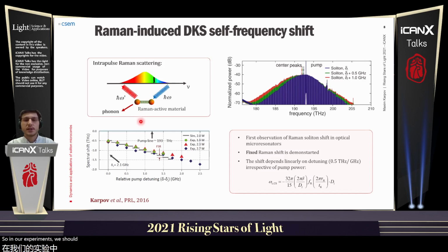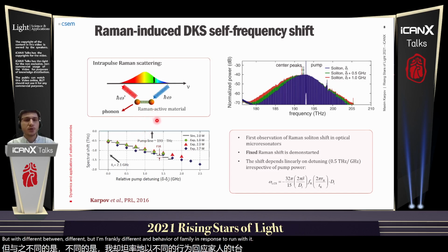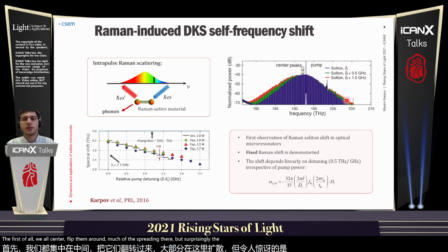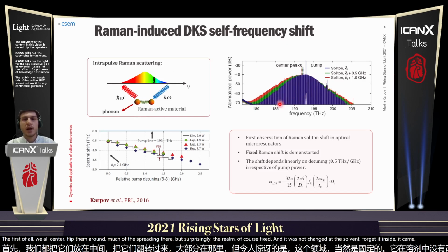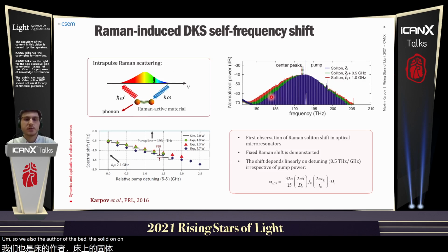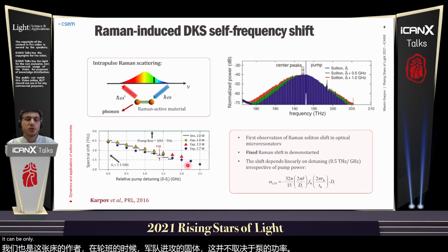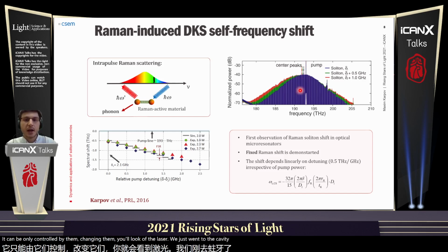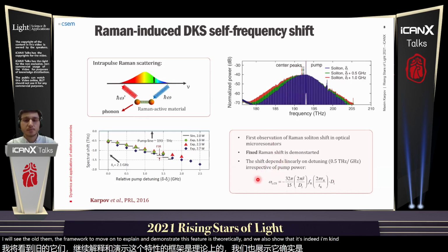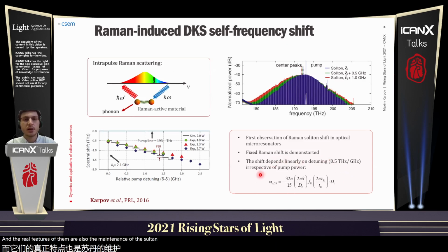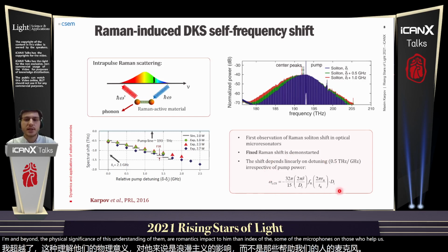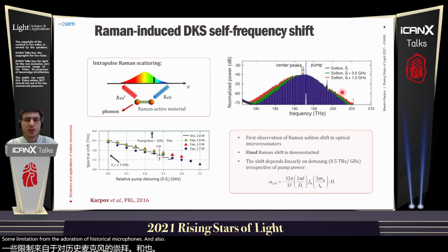So in our experiment, we actually demonstrated that soliton microcombs have a drastically different behavior in response to Raman effects. First of all, we observed that the Raman shift is present there, but surprisingly, the Raman shift was fixed, and it did not change as the soliton propagated inside the cavity. We also demonstrated that the soliton shift does not depend on the pump power, and it can only be controlled by changing the tuning of the laser with respect to the cavity. We also developed a framework to explain and demonstrate these features theoretically, and we showed that it's indeed a real feature of soliton microcombs that the soliton self-frequency shift due to Raman effects is fixed in these devices. And beyond the physical significance of understanding how Raman effects impact the dynamics of soliton microcombs, it also helped us to understand some limitations on the operation of soliton microcombs and also predict their spectrum envelope properties.